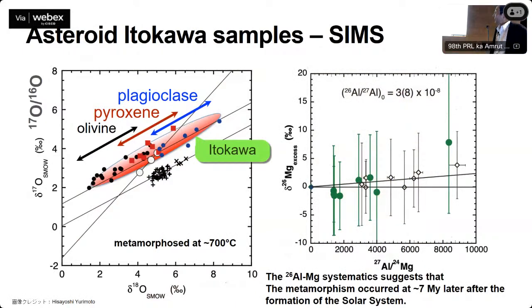And we measure magnesium isotopic ratios. From this magnesium isotopic ratio, we can estimate the formation age. So this 0 is the terrestrial value, and the plot is from Itokawa samples. The average has a little bit of positive value. From this slope, the error is large, but from this slope, the metamorphism occurred 7 million years after the solar system formation. Therefore, the Itokawa parent body formed at a very, very early stage of the solar system formation.